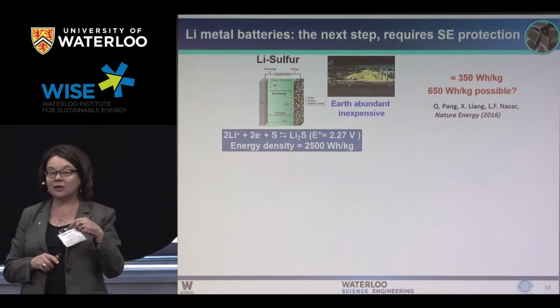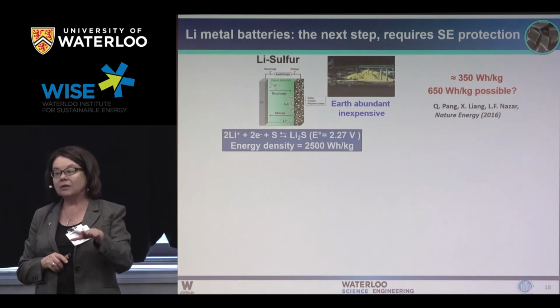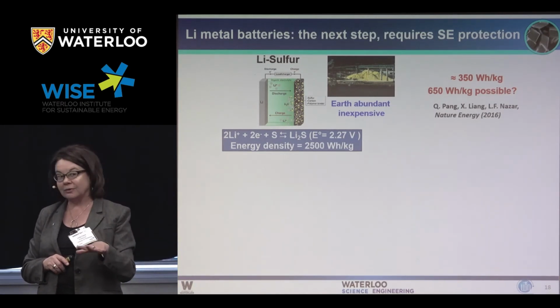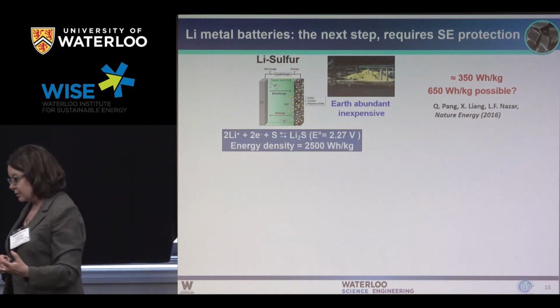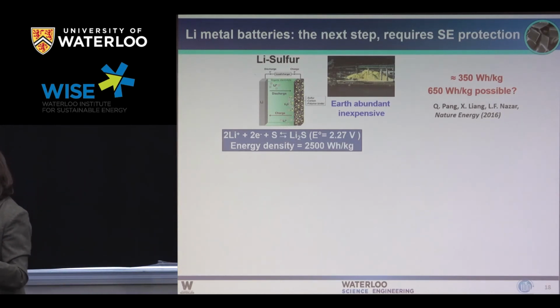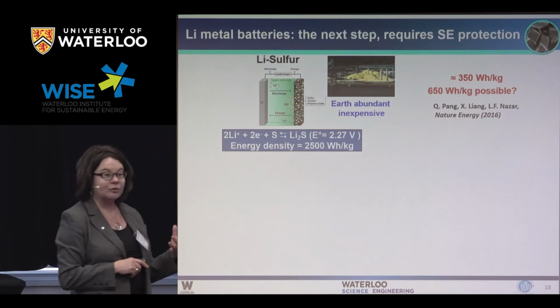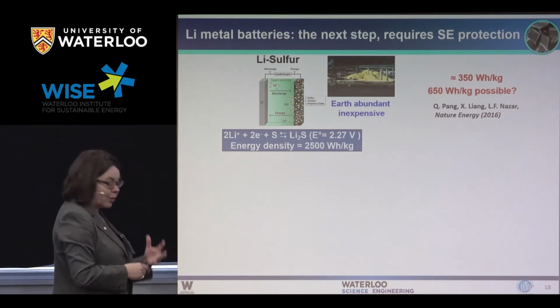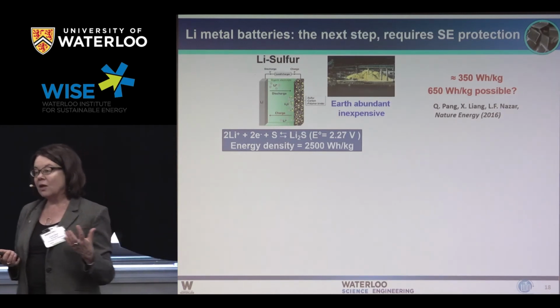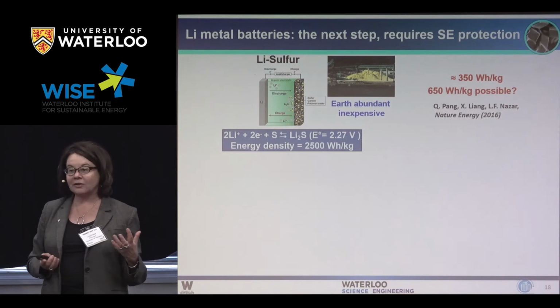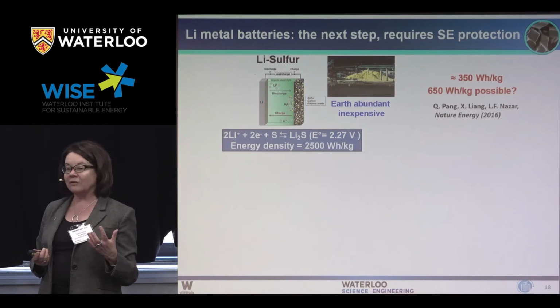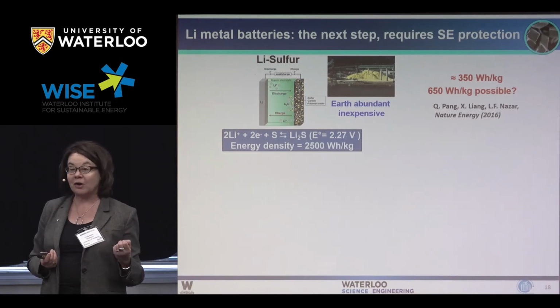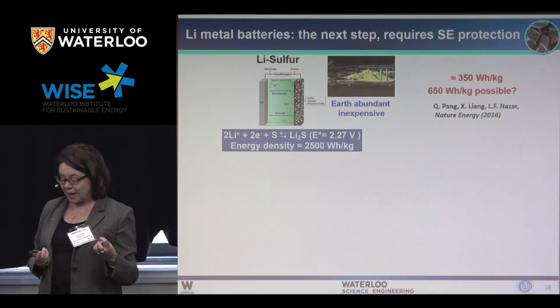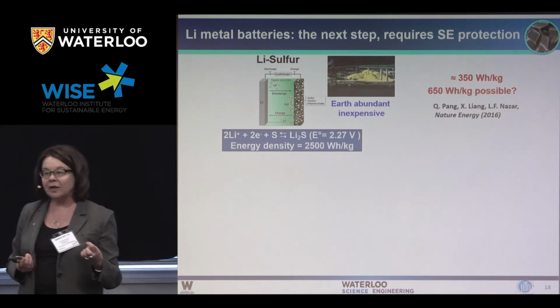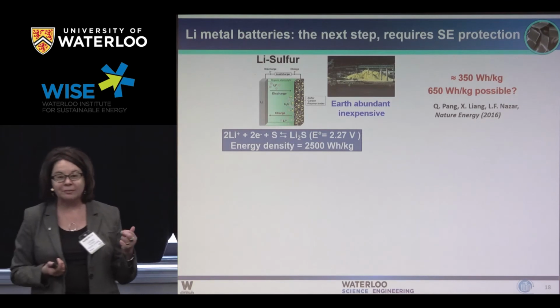So instead of using carbon as your negative electrode, you use a lithium metal anode and negative electrode. And that gives you higher energy density for your cell than anything you could possibly imagine. So why haven't we done this already? Well, this is actually what started Canada off in its history of lithium batteries, which many people may not be aware of. So at UBC, they developed a lithium metal battery based in molybdenum disulfide.